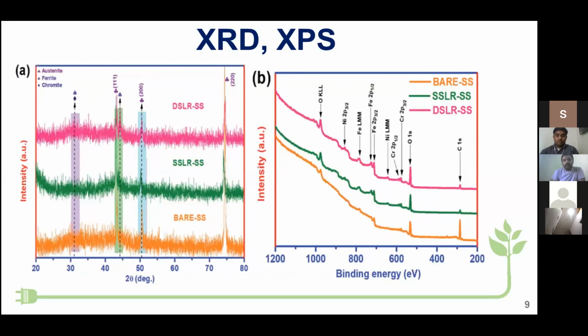So when we irradiate the stainless steel with a laser, the magnetic property also changes, which plays an important role in water splitting. Further, the binding energies of the as-formed oxides are confirmed through XPS analysis. From this spectrum, we can confirm that the binding energies are shifted towards a higher energy region for oxygen, nickel, iron, as well as chromium.